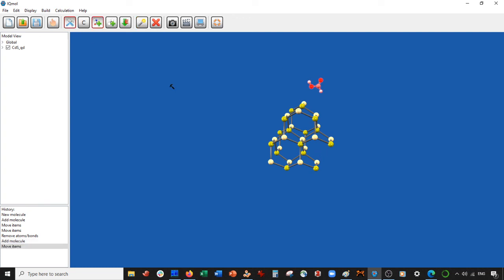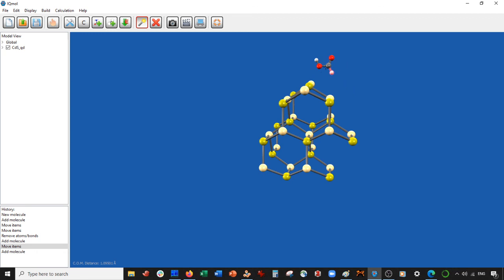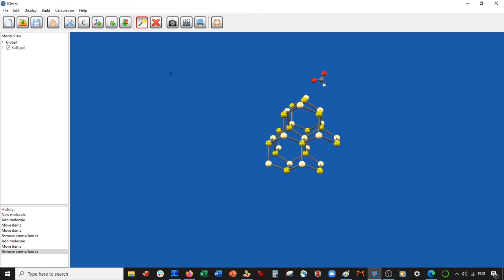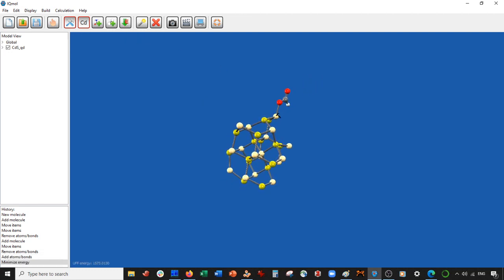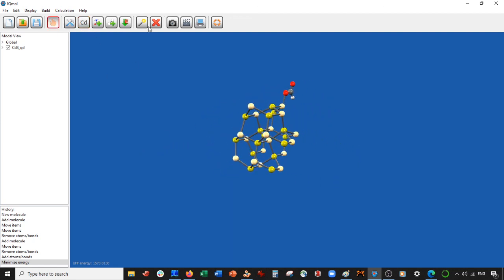To get the minus charge, I simply delete the hydrogen atom bonded to the oxygen on the carboxylic group. By breaking that bond, the electrons remain on the oxygen, giving it a −1 charge. Now I draw a bond from that oxygen to a cadmium atom, select cadmium, then do energy minimization — it's like a fishing hook, it basically just hooks into the surface. I've added one ligand.